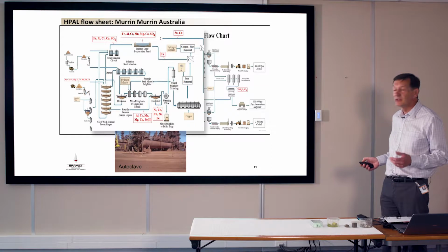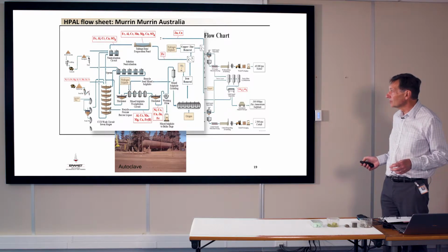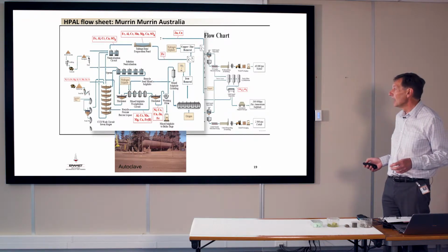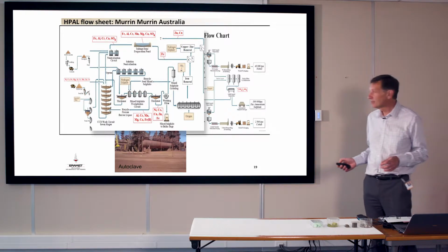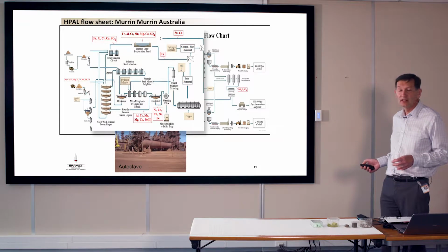On this liquid with nickel content, you first do neutralization of the solution, and you add some hydrogen sulfide here to precipitate nickel as nickel sulfide.